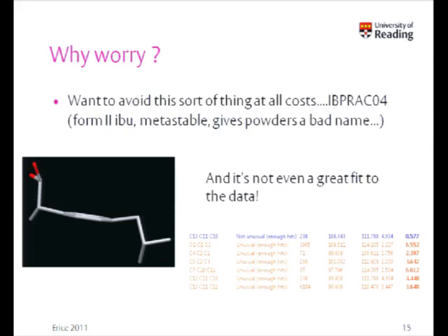So, quite why this got through, I don't understand. It's clearly not right. It is a metastable form. It's produced by cooling a molten version of ibuprofen and then allowing it to anneal for about 8 or 10 hours. The authors actually say that the metastability is probably why it doesn't fit the data, but that's not an excuse. Metastable crystal structure is still a crystal structure. You ought to be able to define it correctly. So that's an example of the sort of thing that we're trying to avoid.